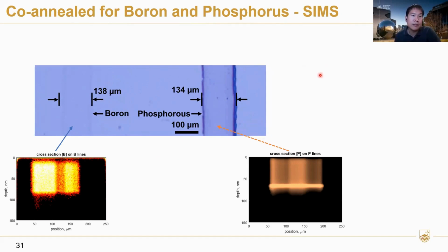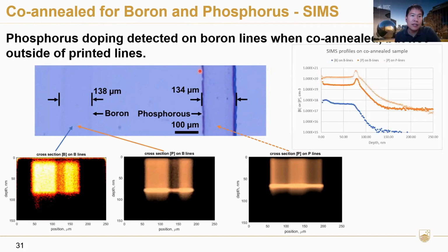At the phosphorus lines, we detect phosphorus, that's also good. But I guess some of you already expected this one: if we start measuring phosphorus at the boron line, we also see phosphorus. So this is not good news for us. There's quite a lot of phosphorus outside of the printed lines.